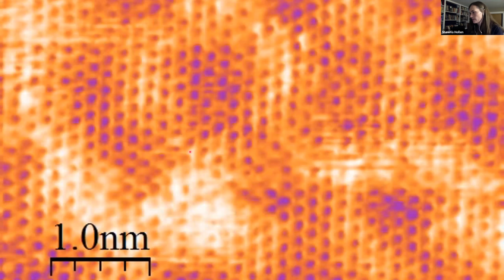Okay, this is another image. This image is from our lab at UNH. This is graphene, the same material, but on a different substrate. This substrate is silicon carbide. And silicon carbide is a nice substrate because we can grow graphene directly on it. So silicon carbide is a crystal that's made of silicon and carbon. So you can heat it up and it will preferentially evaporate the silicon so that you're left with layers of carbon by themselves. And the layers of carbon by themselves will reorganize into graphene. So it's a really nice way to grow graphene. Our collaborators did that for a project, and this is an image that resulted from that.